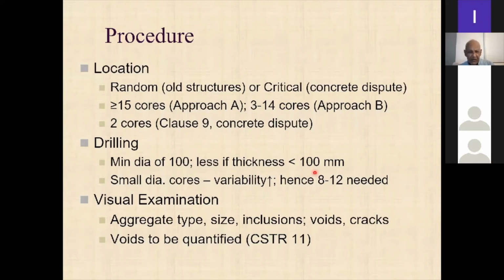So if your thickness of the slab is less than 100, then you have to use smaller diameter cores because your length over diameter ratio must be greater than 1. But if you use smaller diameter cores, your variability will increase. So generally you need more cores, right? Okay. So you can do visual examinations and things like that. And those days, once again, Concrete Society technical report required you to quantify these voids. You can still do that. I mean, that's good practice, right?